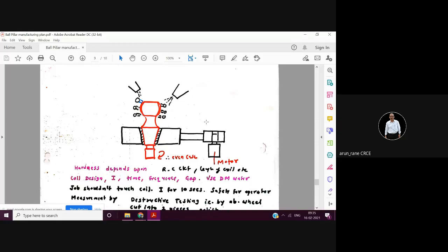You can do grinding or EDM or wire cut, but you cannot do turning, because in induction hardening the hardness that you get is around 58 to 62 HRC, and normally the tools we use, even the carbide tools, can cut up to 45 to 50 HRC. The moment the hardness increases above 50 HRC, it becomes difficult. Then you have to go for special tools. Maybe you will have to use CBN inserts, or diamond inserts. But that is very expensive. Very expensive.